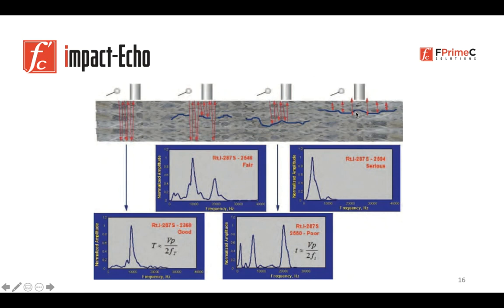And the last one, which happens a lot, is a very good example of delaminations. In the case we have, for example, reinforcing steel corroded by chloride ions or any other aggressive agent or ions, that can cause delamination near the surface. In that sense, since the thickness is very, very low, we cannot really precisely measure the thickness in those areas, because the majority of the stress waves generated by the impactor are reflected off the delaminations. And it's based on the other mode of deformation, because the thickness is very low, and